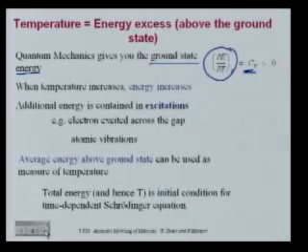This is going to be the key question when you want to deal with temperature simulation. First of all, let me tell you, there is no generic temperature simulation. There is no one way to include temperature, and this is going to be an important message. And the reason is, that extra energy goes into excitations of the system. Okay? It goes into displacements of atoms, phonon modes. It can go into electronic excitations. It can go into defects. And you will have to explicitly choose which of these excitations you include in your modeling.